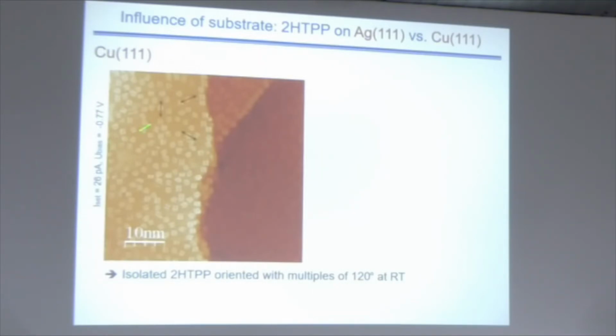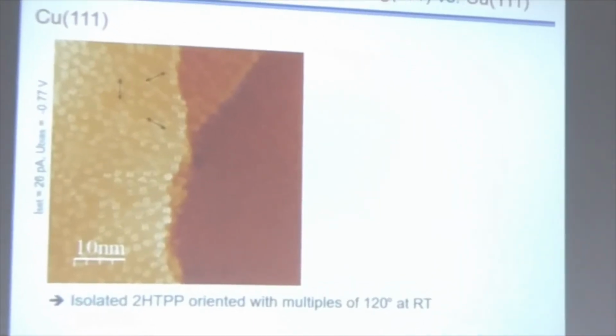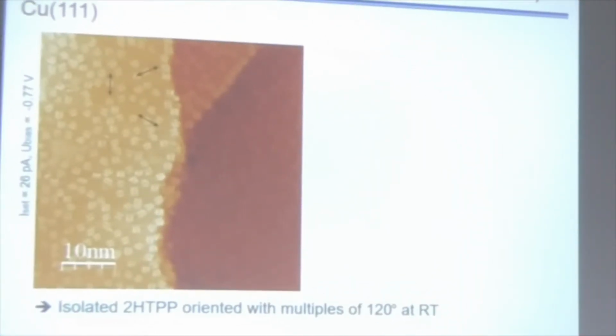This is going up in this direction. This is the same, many of them. And then there are some that are rotated such that they point in this direction, like this one, or this one, and then there are some that are rotated in the other direction, rotated by 60 degrees, so that's the symmetry of the substrate. So obviously what happens here, these molecules want to bind in a very specific site to the substrate. There is obviously a covalent bond of these molecules to the substrate, and therefore they are so highly oriented.